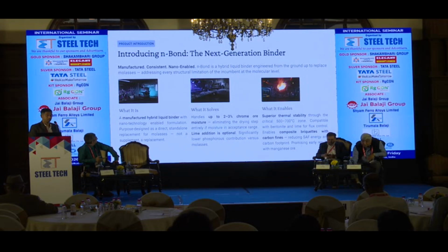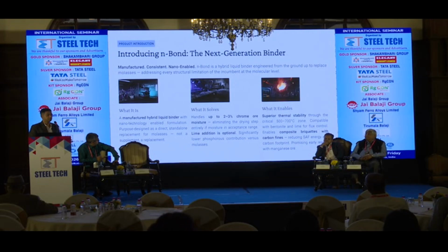What it solves? Now this is very critical because as I mentioned, moisture degrades the lime sucrate bond. Our binder is not dependent on that. So we can handle up to 3% moisture in the system. Where the moisture level is within this tolerance, you can eliminate the pre-drying step. That will again bring you energy and cost savings. What it enables? In addition to the required strength, it also brings superior thermal stability in the critical zone of 500 to 700. That basically ensures that your overall reduction in yield will be at the optimum level as per your design chemistry.